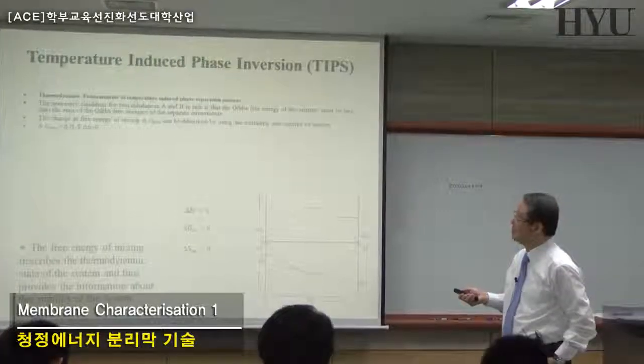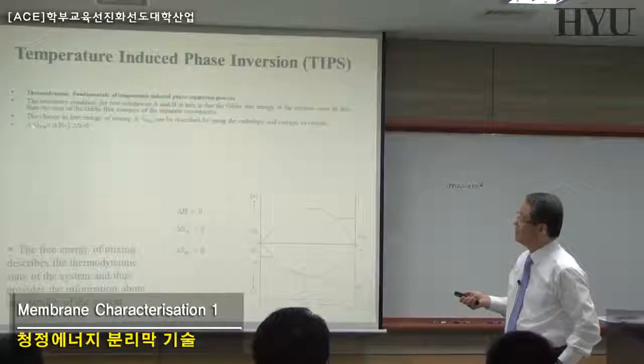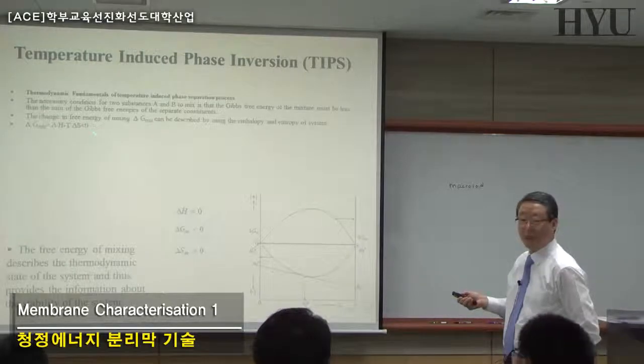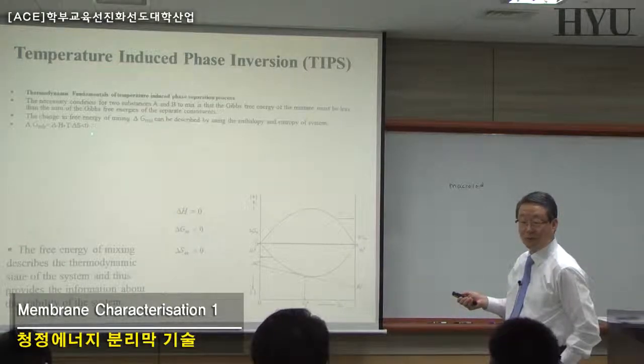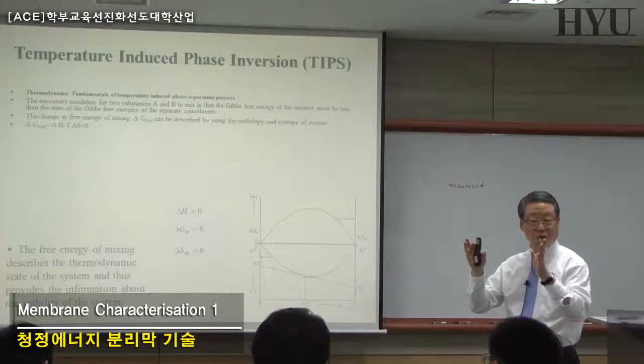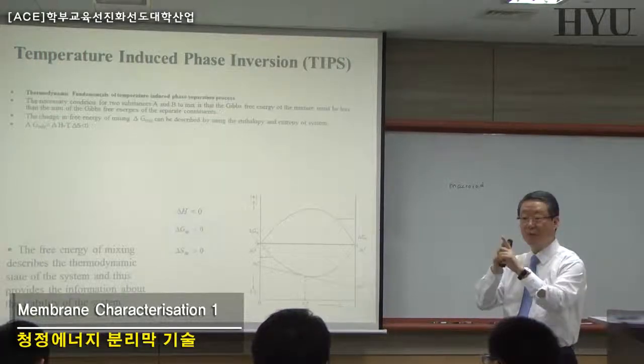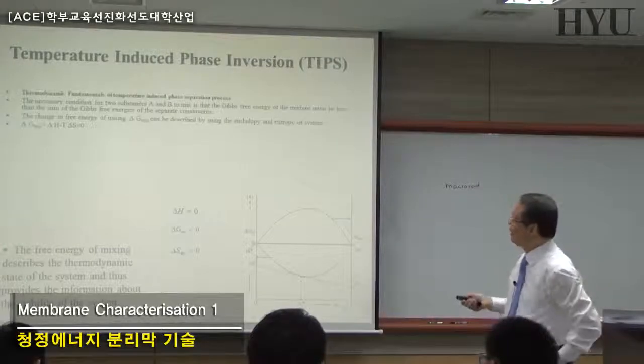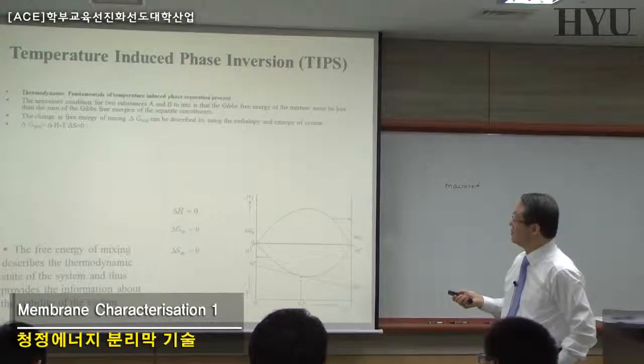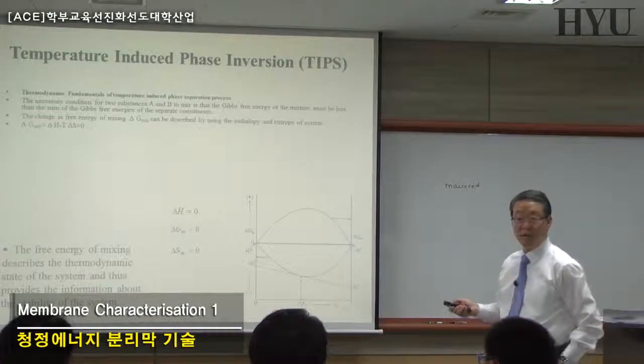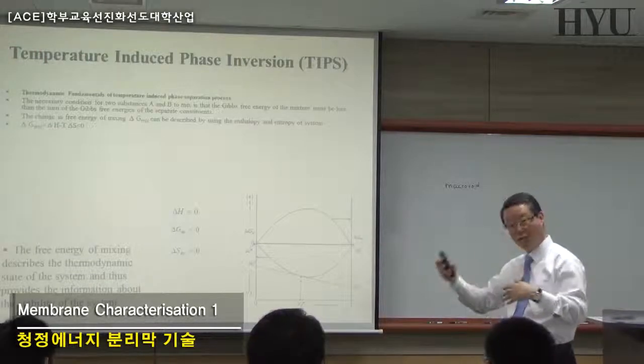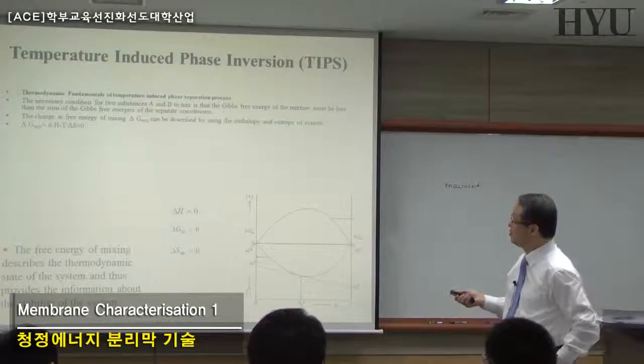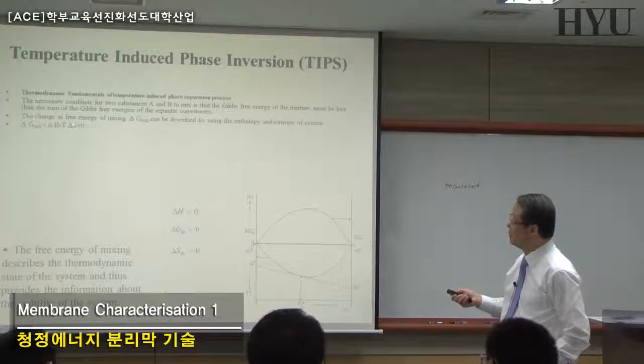So for delta G to be negative, right? To be negative, in this case, delta H should be negative, right? Polymer-solvent interaction is negative. And T delta S is always positive because T is much higher and you increase your entropy anyway. So T delta S is a positive term. So you have a negative second term.